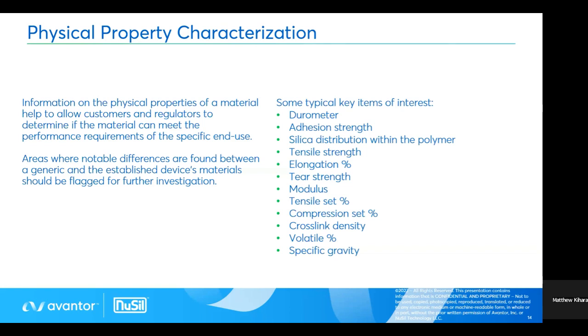strength for applications where adhesion or bonding are needed, filler distribution within the polymer, the tensile strength, elongation, and tear strength of the cured material, modulus at various percent elongations, tensile set at representative elongations, compression set of the cured material, cross-link density of the cured material, volatility of the cured material, and the specific gravity of the cured material. Again, multiple ASTM test methods, ISO standards, and USP standards exist to cover these characterizations, both generically and for specific end uses. Next slide, please.